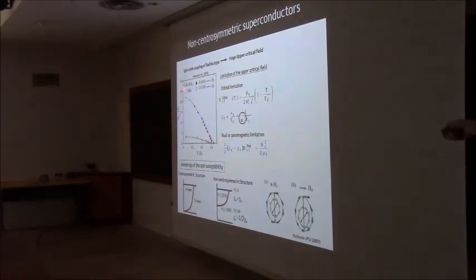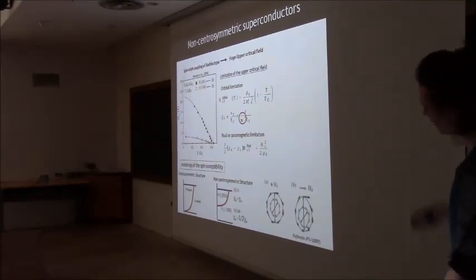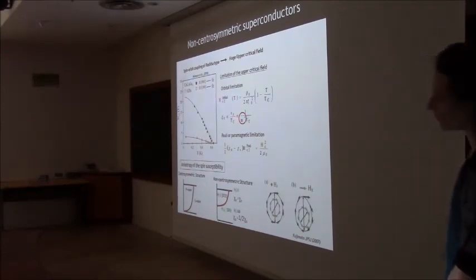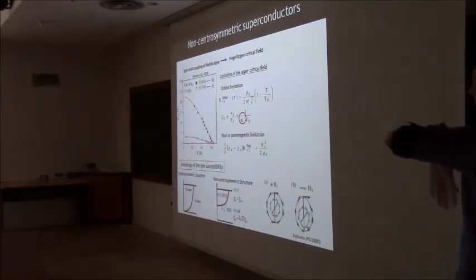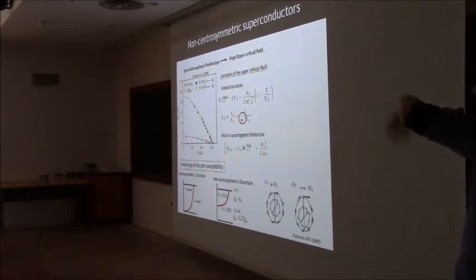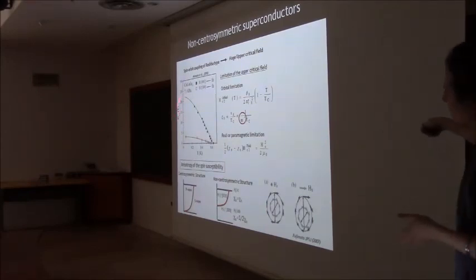And moreover, in this compound, you also have a very, very large effective mass. This belongs to the heavy fermion family, and the effective mass is extremely high at a quantum critical point. So if you have this very large mass, the orbital limitation is also very high. And finally, you can apply an extremely large magnetic field and superconductivity will not be destroyed. This is what we measure here. This is the critical field, and the tendency is now about 30 Tesla for a very, very small superconducting transition. So usually the orbital limitation is here.